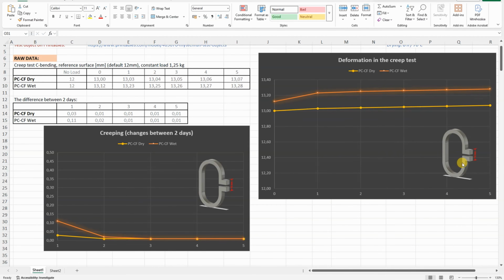On this graph we can see the distance between two reference surfaces, and we can see a little bit more deformation on the wet filament, but the creeping is the difference between 2 days, and that's presented on the second graph. And we can see the creeping is basically minimal, almost zero after day 2. Only on the first day we have a little bit bigger creeping on the wet filament.